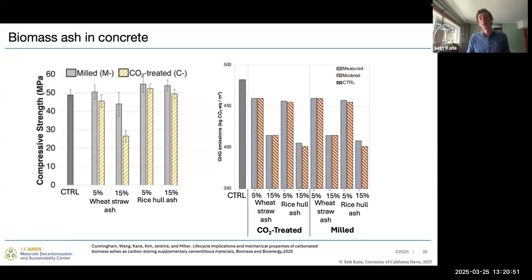When we look at the greenhouse gas emissions on the right, we can see that all of these processes reduce the total greenhouse gas emissions of that production by about the same amount. There's not a big difference between CO2 treated and untreated, and there's not a big difference between the different ashes. This is because the carbon contained in those is fairly small relative to the offsetting of the emissions of the cement production itself. And so that emissions reduction is mostly dominated by how much of that ash we are putting in rather than the carbon stored in the ash itself.